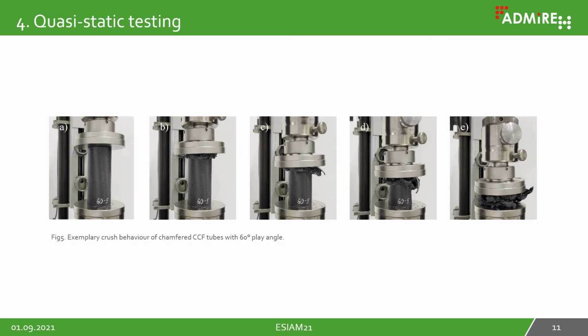Due to the chamfering of the specimen, a local failure is initiated at the start of the crushing process. This leads to circumferential delamination and axial cracks, and therefore petals are formed. After bending the petals even further, the petals will fracture caused by the brittle behavior of the carbon fiber.